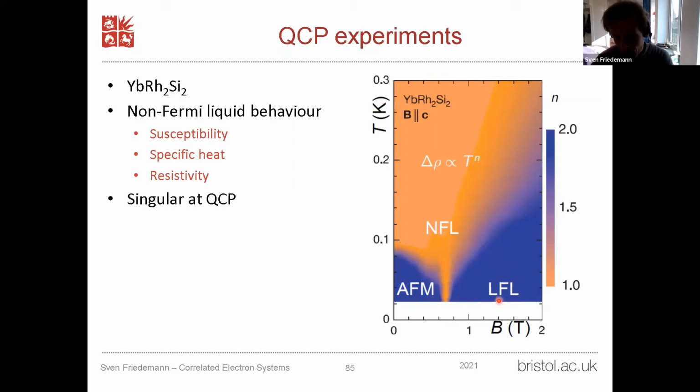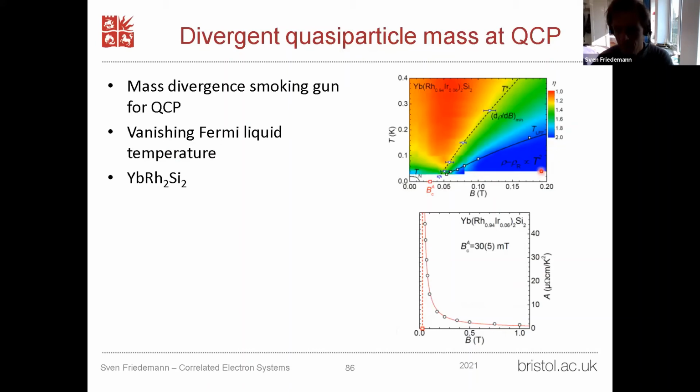If we sit inside that Fermi liquid behavior and get closer to the quantum critical point, we still see the material still feels the effect of getting closer to that. And one way that is observed is, for instance, I've got here measurements which I've done during my PhD thesis. If we measure the resistance inside this regime, we can measure the temperature dependence by measuring resistance versus temperature down here, and it follows very nicely T-squared. That's visible here, for instance, by this blue color code. And one can extract the coefficient of that T-squared behavior, the so-called A coefficient, and that's plotted down here.